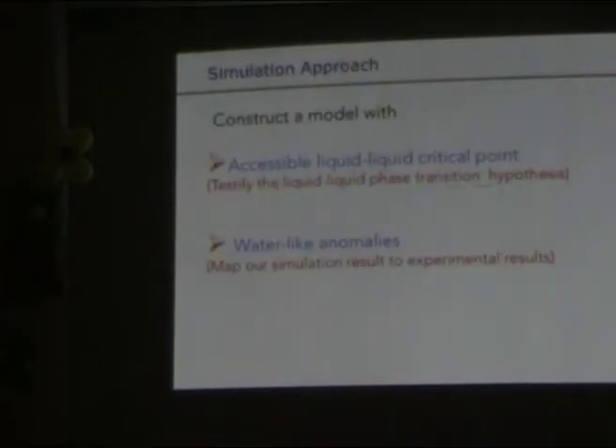So here's the deal. We want to construct a model that has two features. The first is to have an accessible liquid critical point, because we know that in experiment you cannot access it. But we can take advantage of computer simulations. We can build something that has this liquid critical point, and then we can look around at what really happens near the critical point. If we get something that is similar to the experiment data, we can map them to each other. Therefore we can detect whether or not the critical point exists.